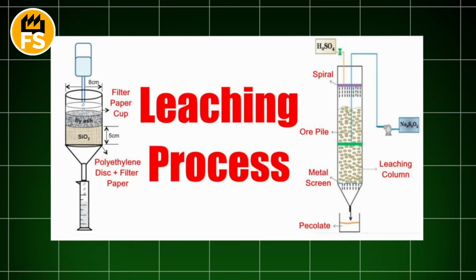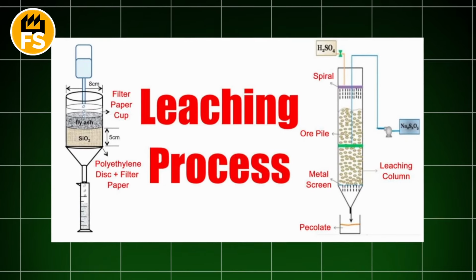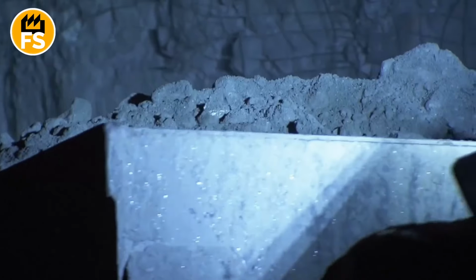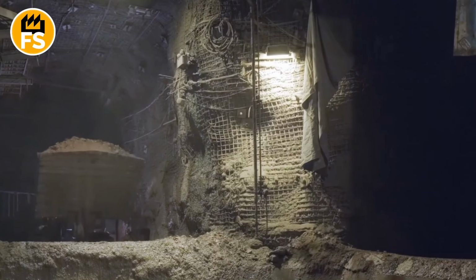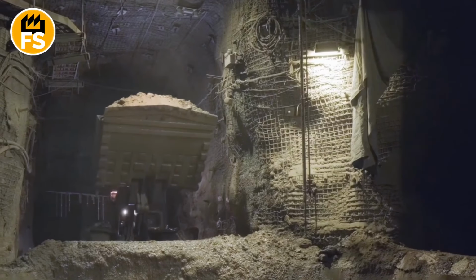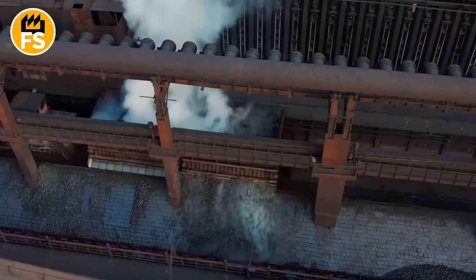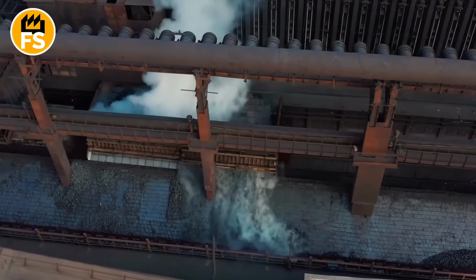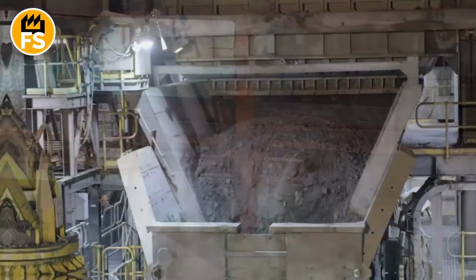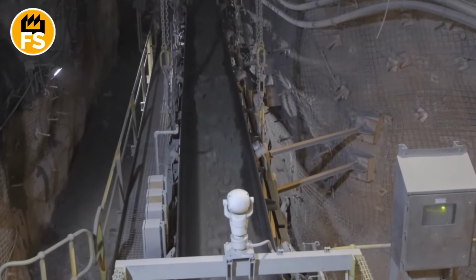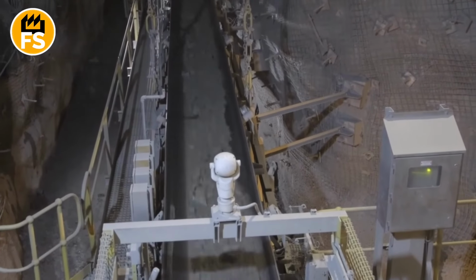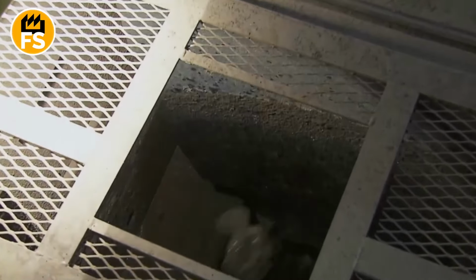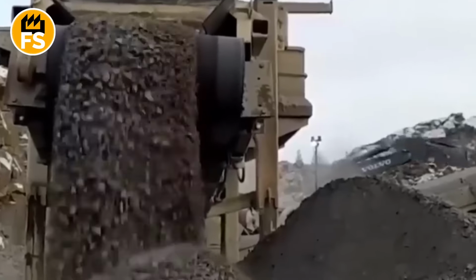And now the real chemistry begins, a process called leaching. This grey sand is mixed with water, forming a thick pulp, and pumped into huge vats the size of a small house. A powerful chemical solvent is added to these vats, most often sulfuric acid. This acid, like a hungry predator, begins to eat the uranium, pulling it out of the solid rock and turning it into a liquid, dissolved state. This process lasts for many hours, while the entire mixture is continuously stirred.